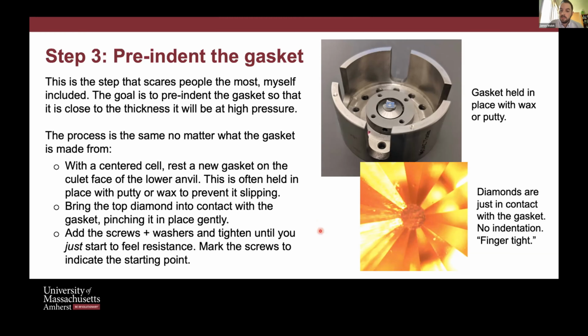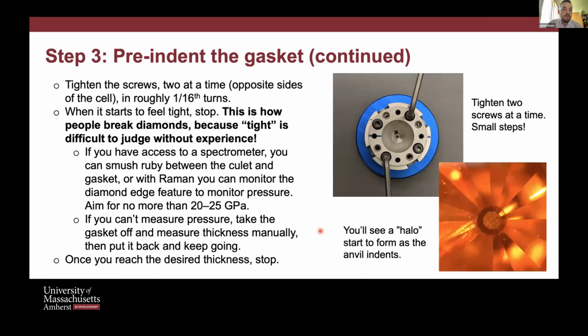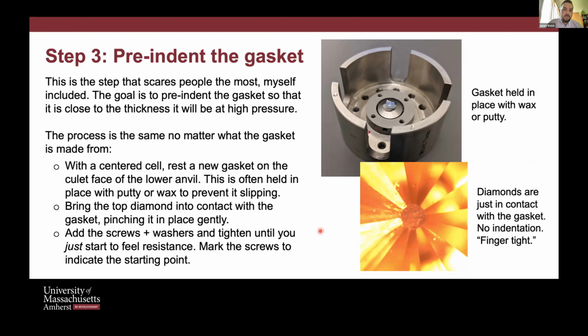You've got your diamond in contact with the gasket. One thing I don't think I mentioned, I did here in the text: this is what scares people the most, because this is usually when people break diamonds. Either the gasket falls off and they bring the diamonds together and they look and they hope to see the rhenium, but they actually see light and broken diamonds. That's one thing that can go wrong. So always make sure that you can look from the side of the cell to make sure the gasket hasn't slipped. That's really the most dangerous part.